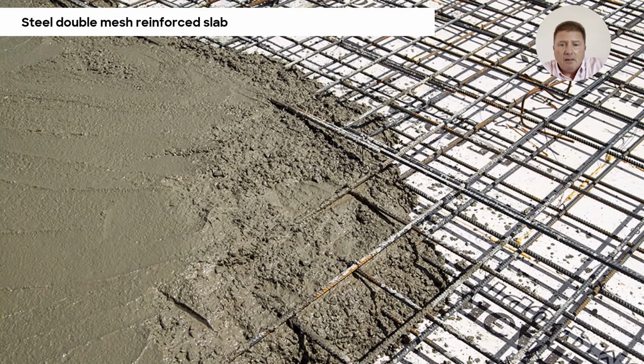Okay, happy with that. But actually, isn't the purpose of the mesh fabric really to control the joint behaviour? What do you mean? Well, for example, if we were to just leave that mesh fabric in that concrete over a large area, laid extremely thin, we're going to get a huge reduction in volume because, of course, concrete shrinks. It's what it does. It uses a proportion of the water in the mix for hydration purposes. The rest is free water, and we get a reduction in volume. So we're going to get cracks. Okay, so what's the answer? Well, we put saw cuts in.